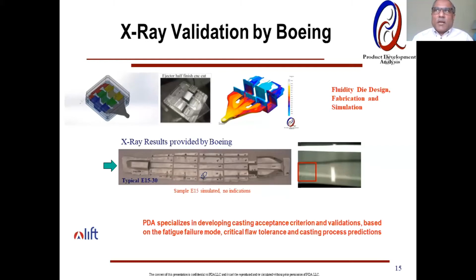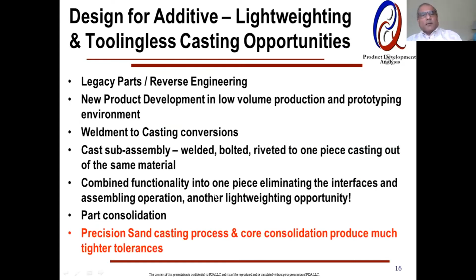So what I've been publicly talking about is you should look at the component from the high stress area, the service life, and the fatigue failure mode. And by doing critical flaw calculations, then you back calculate and come up with the casting acceptance criteria. And that's where ICME based modeling simulation come out very valuable. So what you do now is you have a casting with zoning with different levels of severity for different types of defects. Now you are giving something to manufacturers that they can make cost effectively, consistently. And so I just wanted to dwell a little bit on that.